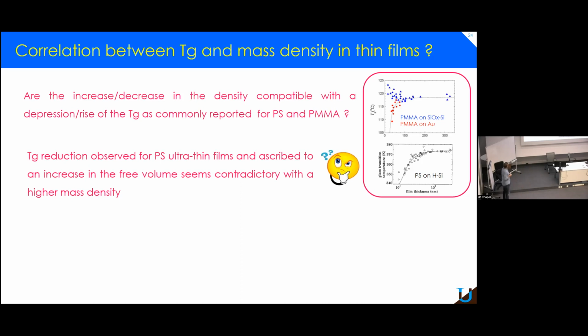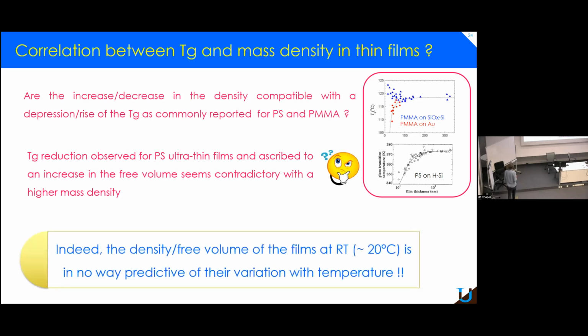Because usually the glass transition, at least in the papers, is ascribed to an increase in the free volume. At least that's the way people explain the decrease of the glass transition of polystyrene with the thickness. But in fact, the density or free volume of the film that we measure at room temperature, 20 degrees, is in no way predictive of its variation in temperature. So it's not because the density at 20 degrees is different that, close to the glass transition, the free volume will be different.